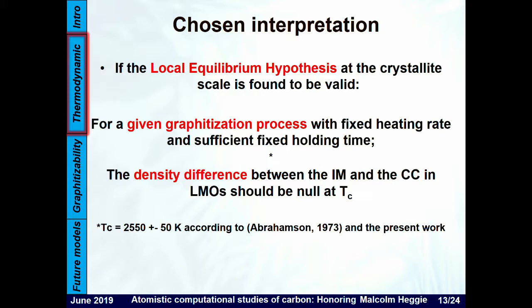So I made the calculation for the prismatic surface at around 2600 Kelvin, but other people, such as Abrahamson, made a similar calculation for the basal surface energy at around 2500 Kelvin. The exact temperature is not very important. It's the existence of this temperature which is. So at the end of the day, I decided to develop my graphitization model considering a critical temperature of 2550 Kelvin with an error bar of 50 Kelvin.